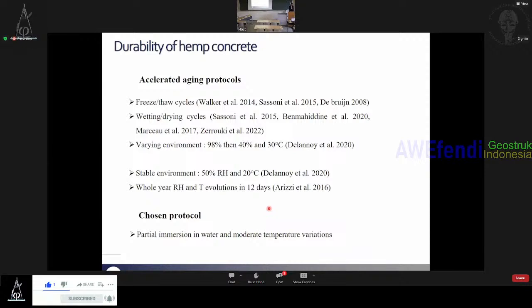So what we propose in this work is to evaluate the durability of hemp concretes through a different approach, which we think would be more representative of what materials undergo in their life cycle. We propose a partial immersion instead of a complete immersion, as we can see in the previous works. Indeed, when they are in building walls, they undergo only partial immersion through capillary rise. So that's why we chose only partial immersion and a moderate temperature variation.